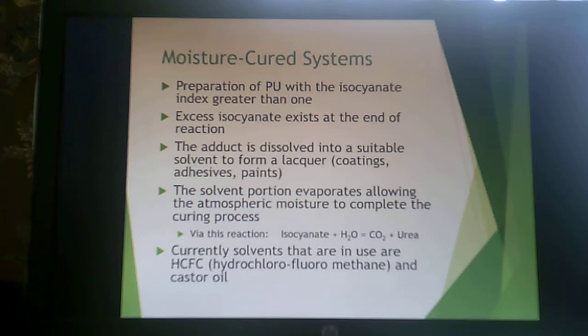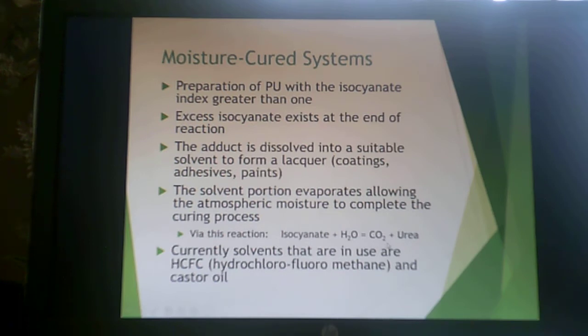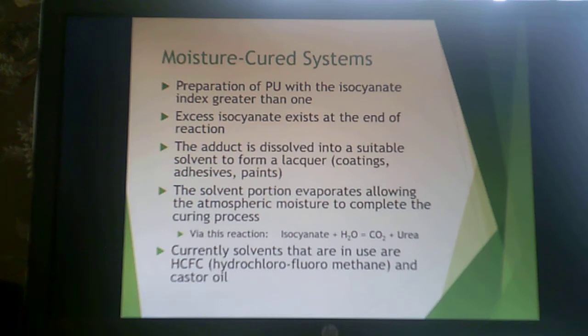This is usually used when applying a polyurethane coating to a piece of furniture. You apply it, and your isocyanate reacts with atmospheric moisture to give off carbon dioxide bubbles and form ureas as cross-linked compounds. The CO2 can evolve through a thin coating up to the surface. If you apply it really thick, you'll see bubbles. But with nice thin coats — say, five 2-micron coatings to achieve a 10-micron coating — you let the first one cure, reapply the next, so the carbon dioxide can evolve and escape.